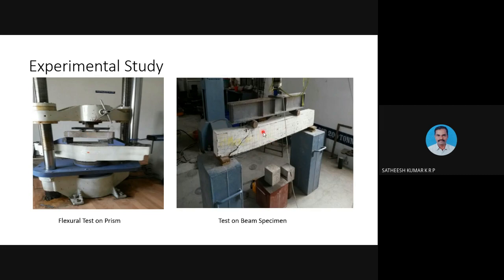And for the beams, we used a loading frame with a hydraulic jack, and we applied 2-point loads. We were expecting a pure flexural failure, but what we arrived at is a combination of shear and flexure failure, and the shear failure is observed to be predominant here. The reinforcement which we used for this beam is 2 numbers of 10 mm diameter bars, both at the top and the bottom, and the shear reinforcement is 6 mm rods at 100 mm center to center. The shear capacity and the moment capacity of the beams are found to be much closer to each other from the analysis, and experimentally also we got the same results.